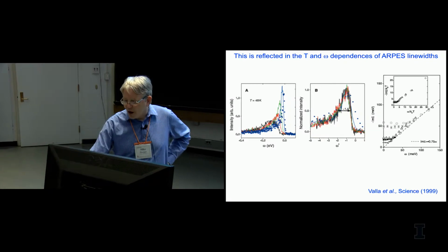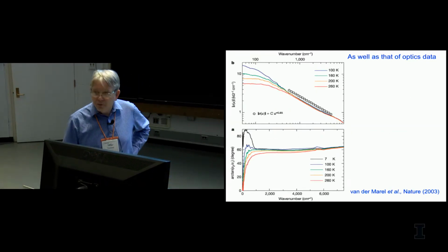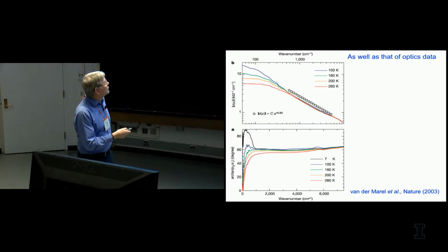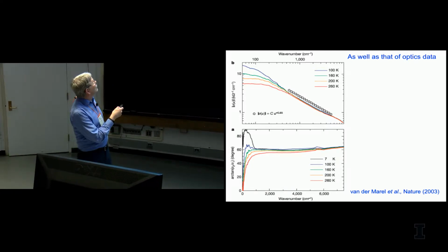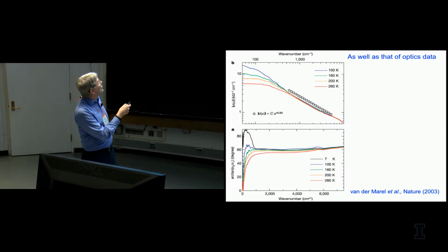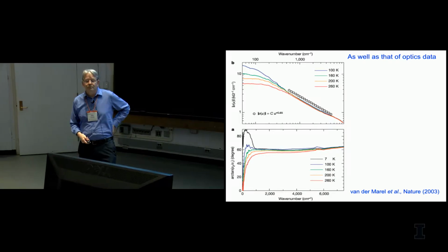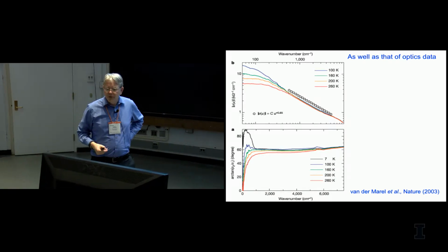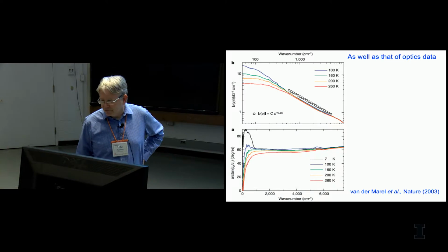And you also see this in optics. This is a rather famous paper done by the next speaker, Dirk van der Marel. And if you look at sigma of omega versus omega, you see these very strange power law behaviors indicating that the normal state is anomalous.